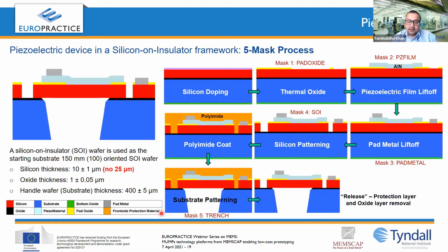And then the fifth mask, that is the trench mask, is used to pattern the backside of the wafer, that is, the trench, to etch the substrate. Once the substrate is patterned and etched, it is followed by the removal of the oxide by the dry vapor HF process, and before that the protective layer is removed by another dry etching process. So the designer gets their devices.